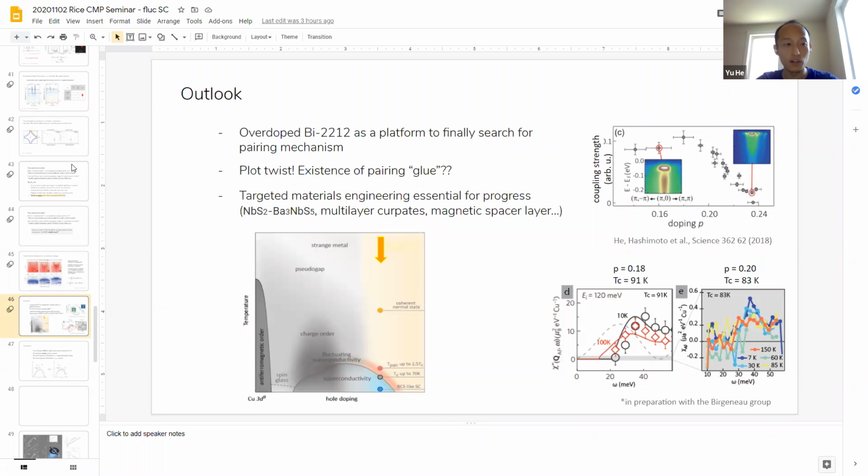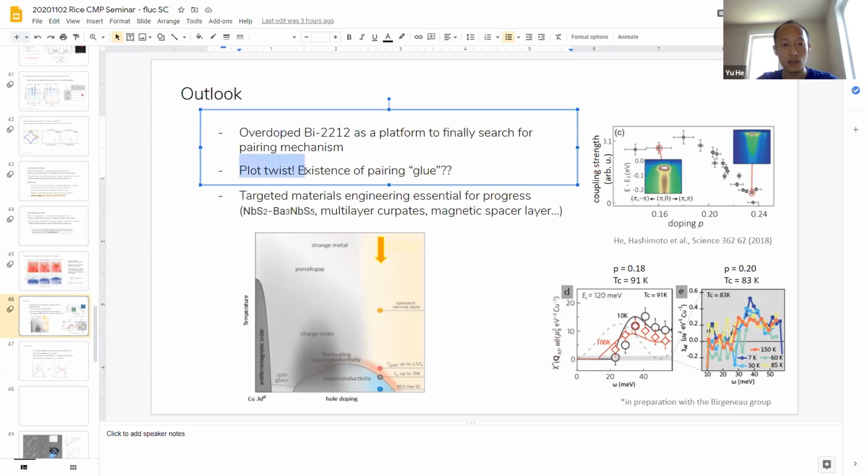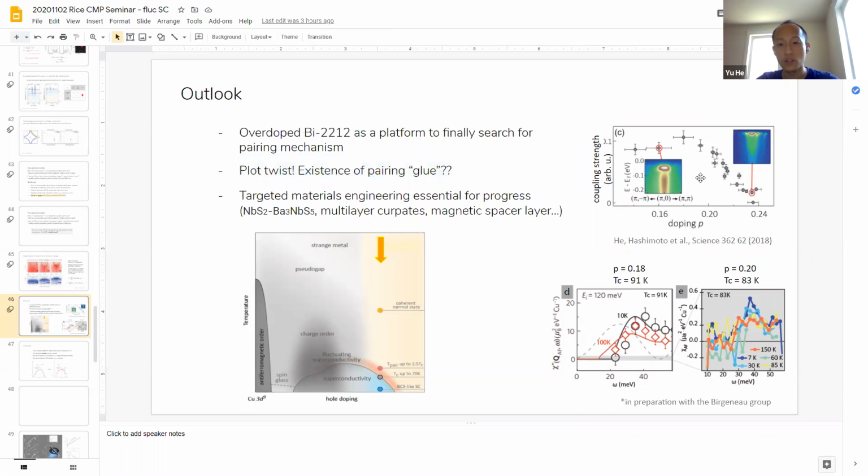It was more, when I initially structured the talk, a next step. The reason was because we checked the most prominent electron-phonon coupling type in this overdoped region, and it's almost non-existent at 22% doping. And then we also measured the magnetic excitation in those systems, and it's more than an order of magnitude weaker than what you would have in a near optimally doped sample. So the two leading candidates of low energy pairing boson are seemingly out of the picture.